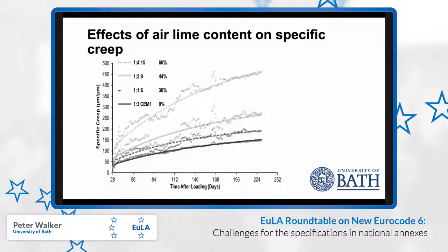So this graph here presents the specific creep strain for the mortar specimens. So these 18 millimeter diameter, 36 millimeter high specimens. First of all, the test ran for over 6 months. And you can clearly see, particularly in some of these specimens, quite a high degree of noise in the response. In some of these tests, we struggled to maintain precisely constant environmental conditions, and so some of this noise was a result of environmental changes. We were able to monitor that because we also measured movement of specimens without any load on, in the same way we did with the masonry wall tests.